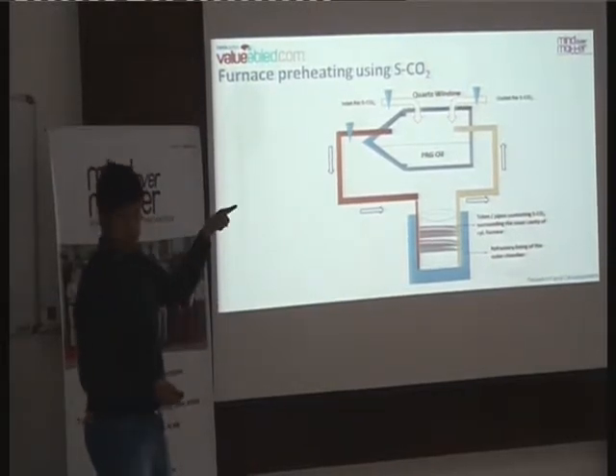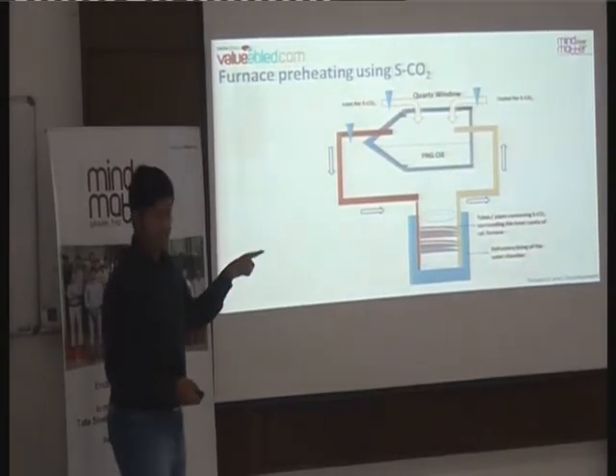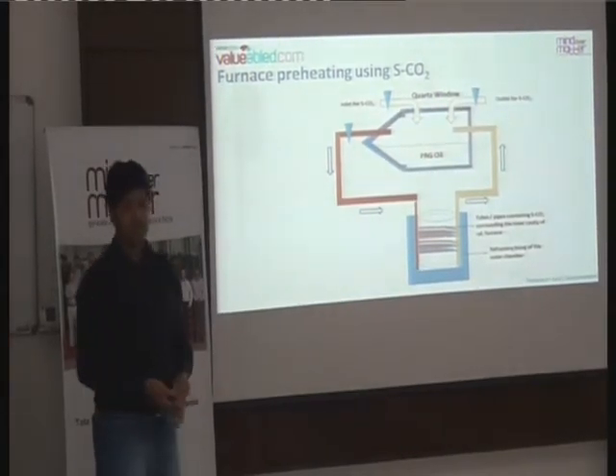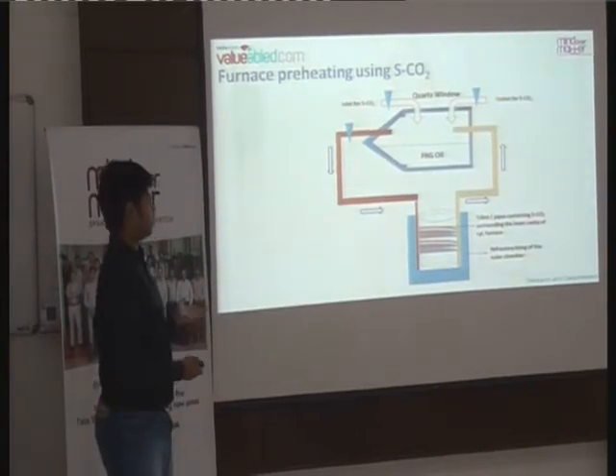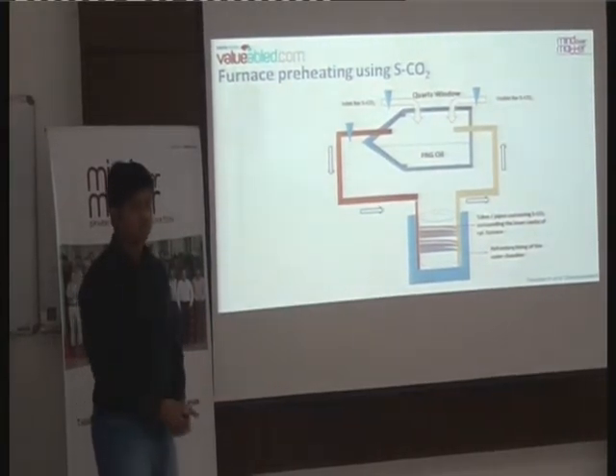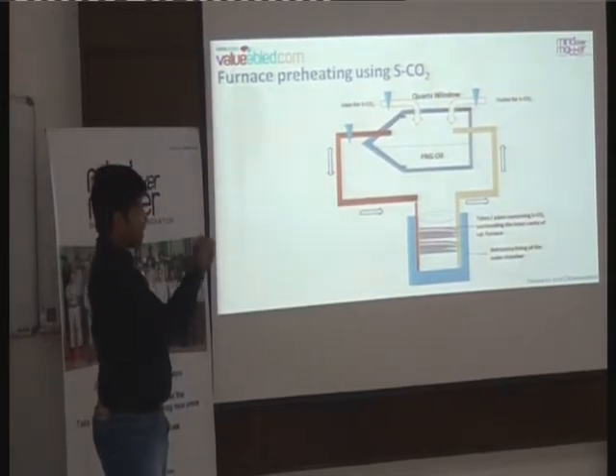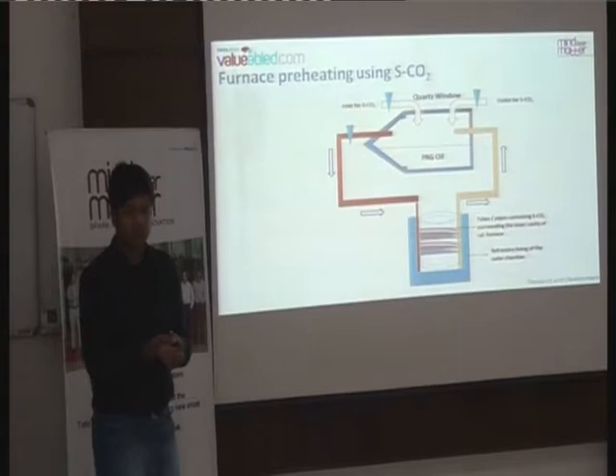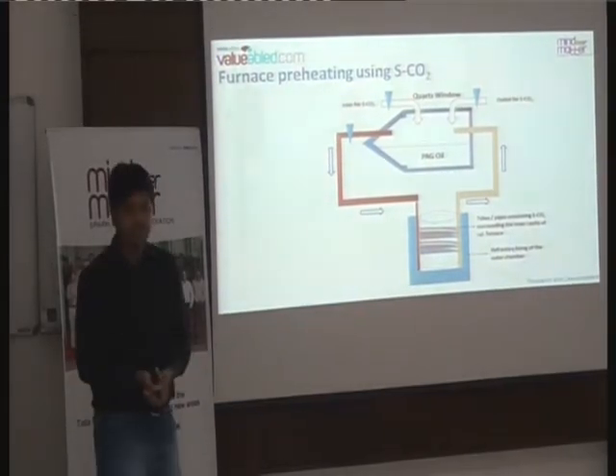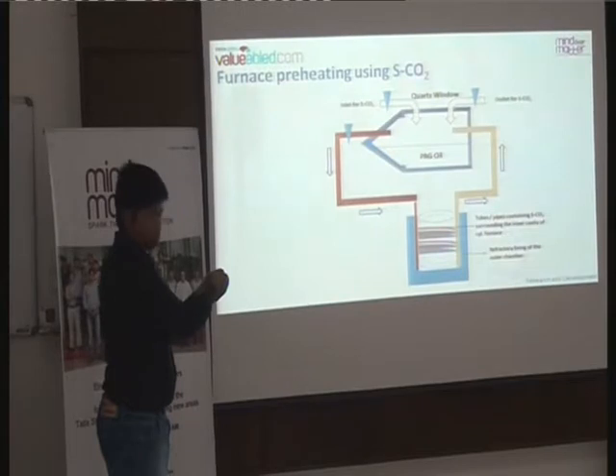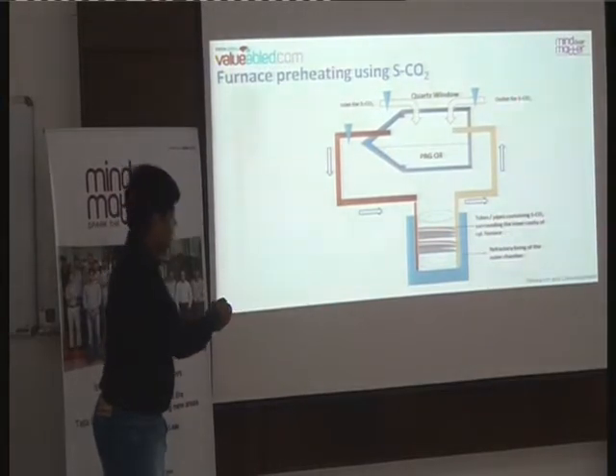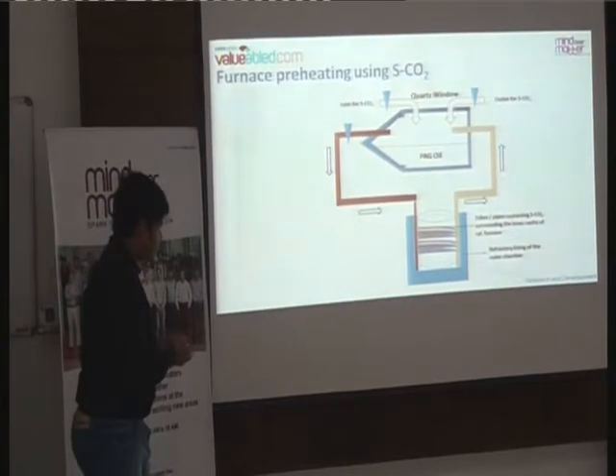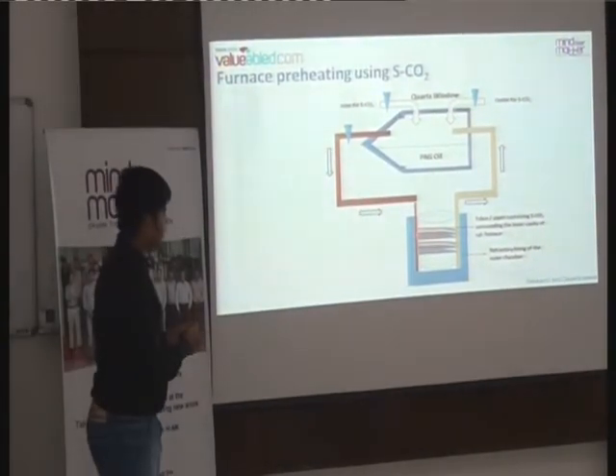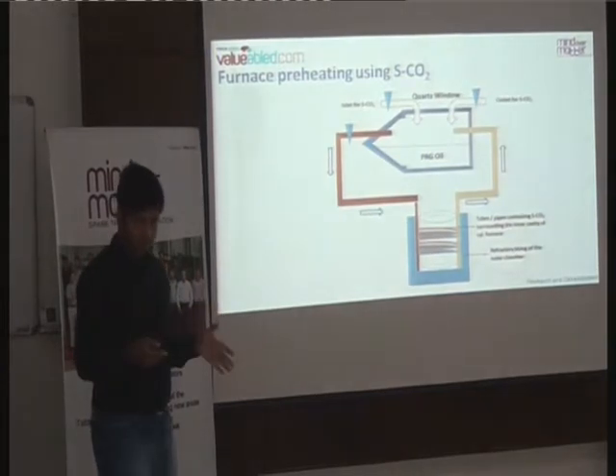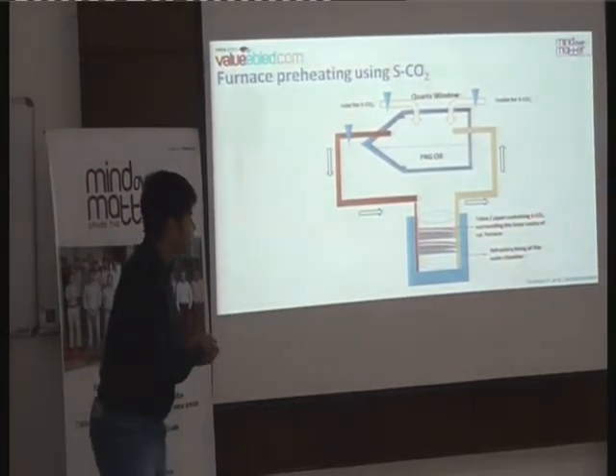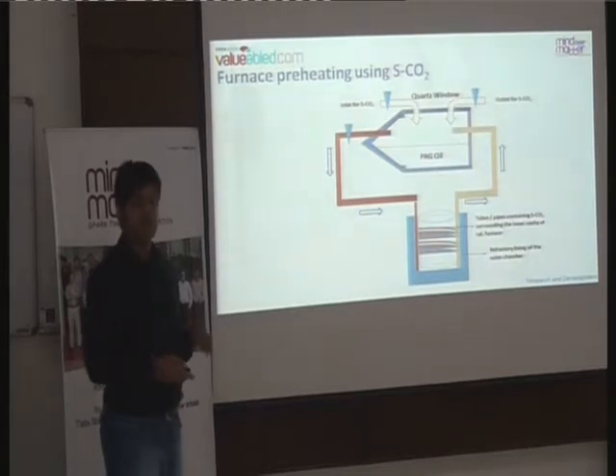From the inlet, the supercritical carbon dioxide will enter, which contains PAG oil. The reason for using PAG oil, that is polyalkylene glycol oil, is to maintain convective heat transfer so that heat losses will not occur. And the temperature when it increases is nearly about 600 degrees centigrade. That has been passing through this red color tube, and this is a special type of setup which we have thought of. The outer blue color is a crucible chamber, and the outer cylinder is completely fixed, which has internal coils, internal tubes, through which the supercritical carbon dioxide will pass.